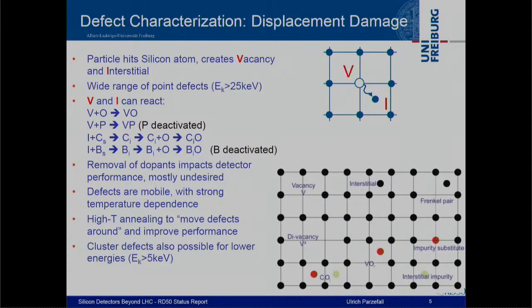In these cases, the dopants you originally had get deactivated, and this will have an impact on your detector performance, which in almost all cases is undesired. I should also point out that these defects are mobile with a very strong temperature dependence. So the warmer your detector, the more these defects move around, and this is something we call annealing, which can be used to improve your detector performance, as you'll see later.